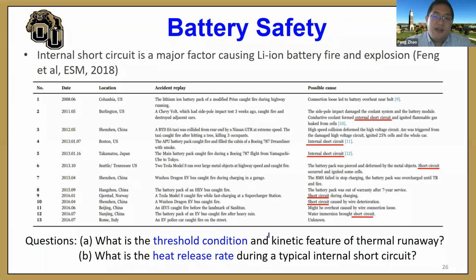As reviewed in this table, you can see that most of the electric vehicle or plane accidents are caused by internal short circuit or external short circuit of lithium-ion batteries. What happens in such a process is that the short circuit tends to create a hotspot within a battery pack. That hotspot tends to trigger some unwanted reactions in the battery material, including the electrode and the electrolyte.